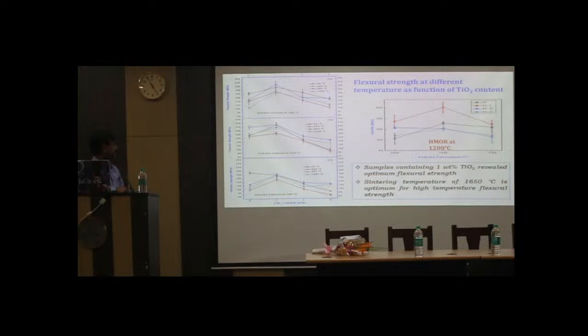1% titanium gives the better flexural strength at different temperatures. And if you compare the hot modulus of rupture at 1200 degrees centigrade, why 1200? Because the borosilicate glass that is used to immobilize high level nuclear waste is used at around 1200 degrees centigrade. So the application temperature is 1200. That's why we kept the temperature at 1200 degrees centigrade and evaluated its thermomechanical properties. So samples containing 1% titanium reveal the optimum flexural strength. And the sintering temperature of 1650 gives the optimum strength.